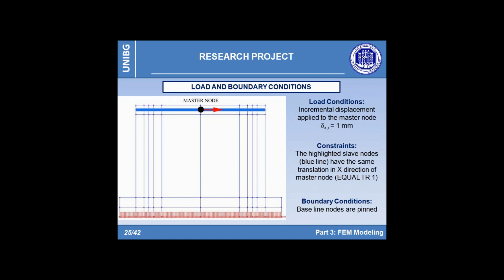This is the last slide regarding the finite element model, showing the applied load and the boundary conditions. All the simulations have been performed applying a displacement of 1 millimeter amplitude to the center point of the top beam. Then a pushover analysis up to 60 steps has been carried out using both displacement and force control with a tolerance of 1% for both parameters.